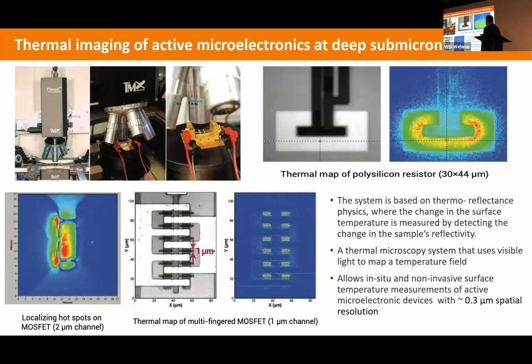The other thing that we put together here is the thermal imaging for active systems. So the beauty of this system is that we have a very good spatial resolution. And that's the beauty, of course. So what is the drawback of this? The drawback is that we need a way for the light to be reflected on the surface, so we have some sort of metal in there. But most of our devices have metal, so we're not too concerned about that. Look at the size of this, it is 1 micron. So we can get some of the temperature profiles of a device in operation using this tool. The temperature resolution is about 1 degree Celsius. So we have great spatial resolution and very good temperature resolution. How does this work? Basically, by looking at how the reflectivity of that metal surface changes.